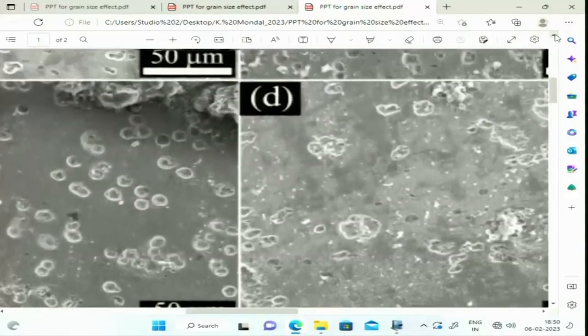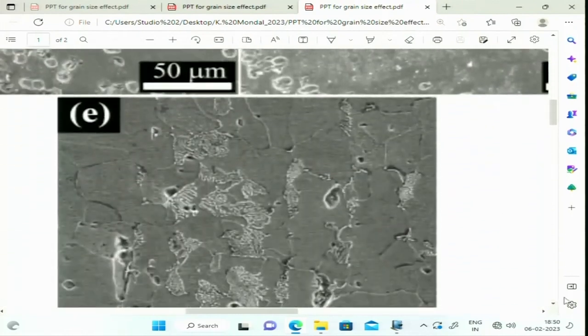Similarly for the fine grain, the same observation can be noticed. So, it clearly reflects that grain boundary sites are basically the initial attack sites. Now, the question is, what have we observed in that paper? We observed that this particular material in 3.5% NaCl solution did not show any passivity. It showed active behavior all the time, and in some cases we saw both cathodic and anodic processes are activation controlled, and in some cases we saw that the anodic process is definitely activation controlled, but the cathodic process could be concentration controlled. So, both are possible, but it does not show any passivation. We also saw that the 4 micrometer grain size material has the highest corrosion rate, and as we increase the grain size, the resistance to corrosion in 3.5% solution also goes up.